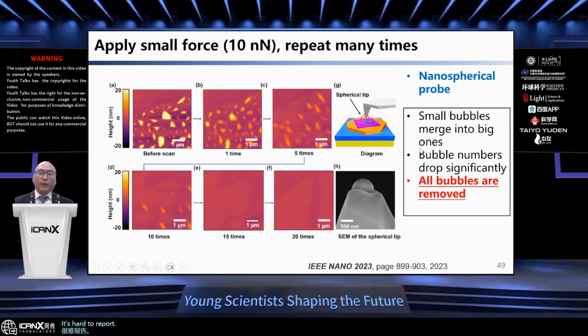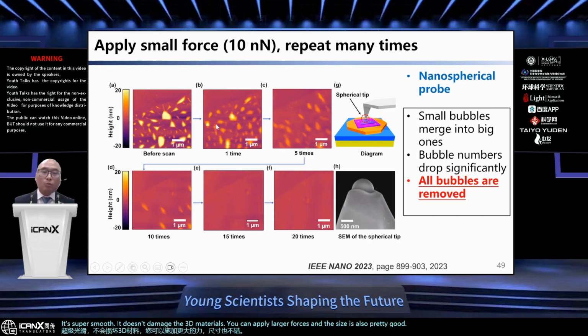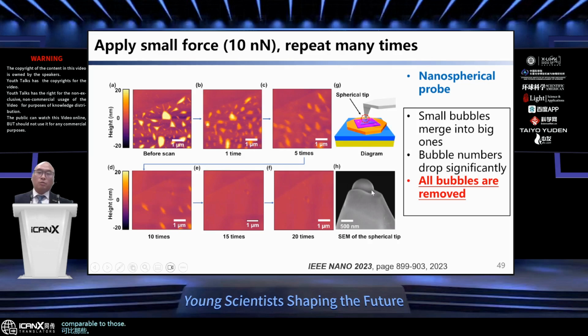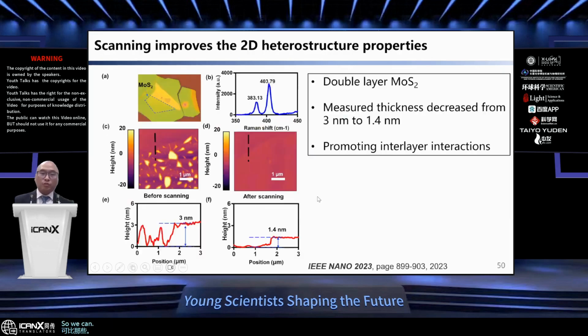But for nanospherical probes, because it's hollow, it's super smooth, it doesn't damage the 2D materials. You can apply larger forces, and the size is also pretty good, kind of comparable to those big bubbles. So we can remove all the bubbles.